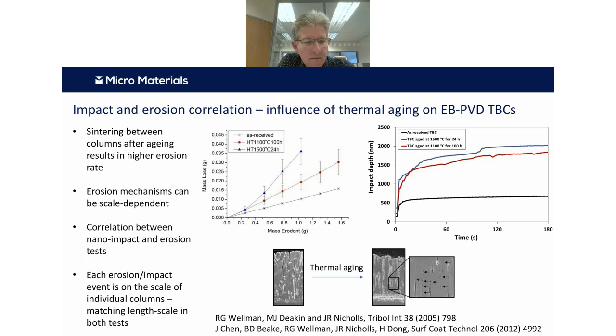So this is a little bit of a complicated slide showing how we used this test technique in the past for these E-beam PVD TBCs. And in this work with Cranfield, we were trying to understand whether the test technique could simulate the changes in erosion wear resistance that happened after thermal aging. So what you see in the middle is erosion tests that Cranfield did in collaboration with Rolls-Royce.